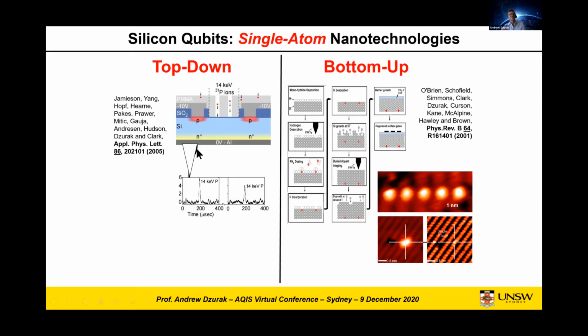An alternate approach to configuring individual phosphorus atoms in silicon was a technology developed by Professor David Jamieson at University of Melbourne and ourselves at UNSW. And the idea here was to use a more conventional way of putting phosphorus atoms into the device, and this is ion implantation. So ion implantation, where you accelerate phosphorus ions and fire them into the chip, is the standard way that phosphorus and other dopants are put into silicon devices in the microelectronics industry. What we devised was the idea of